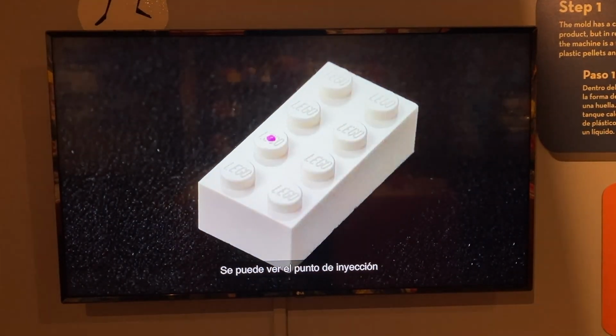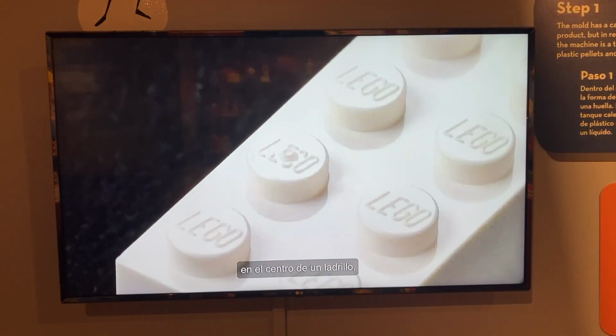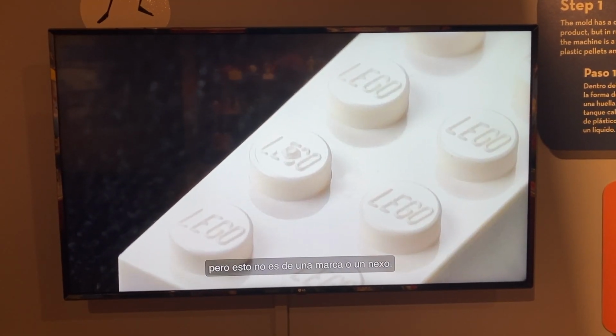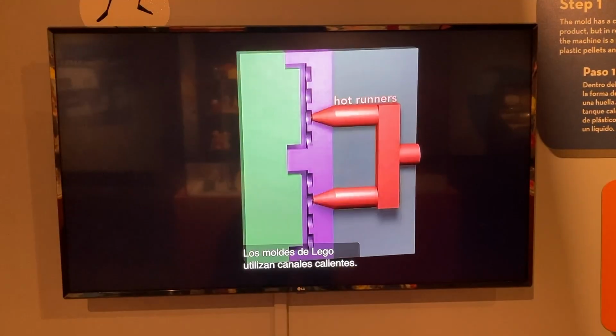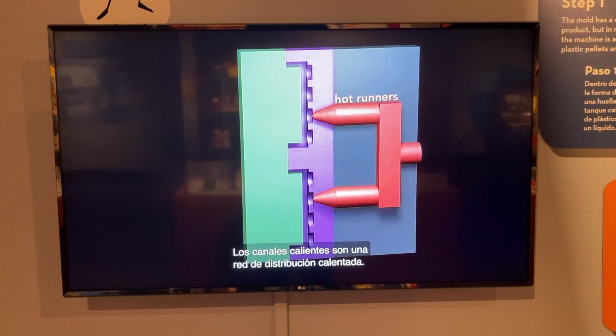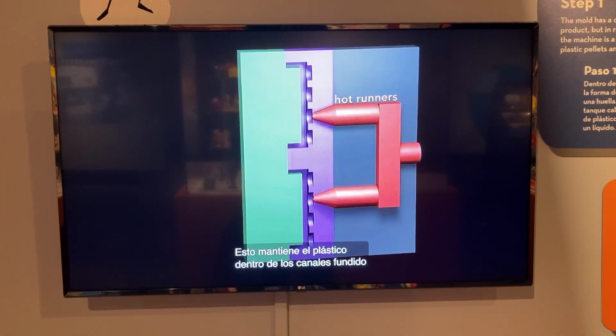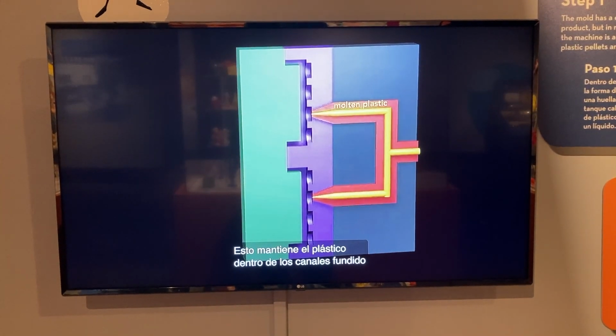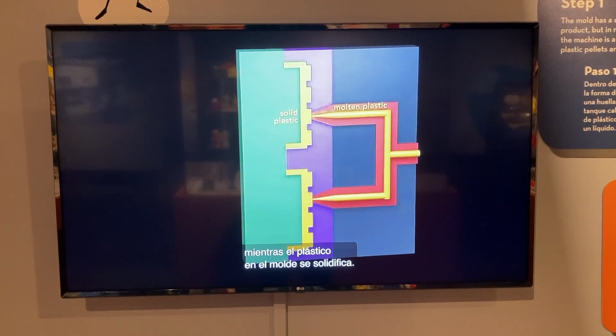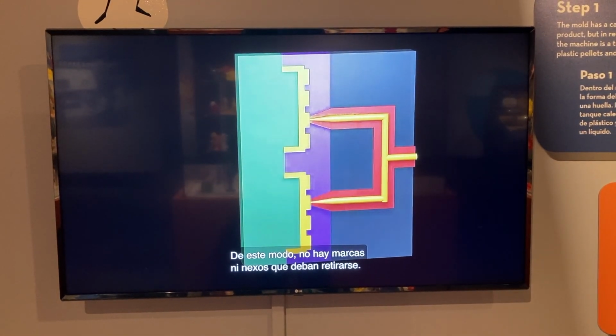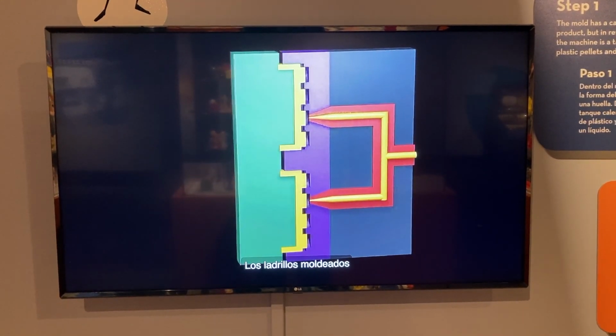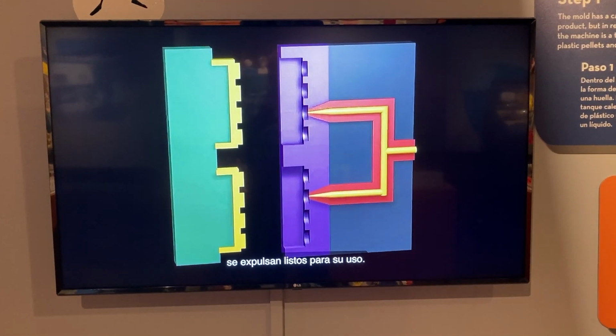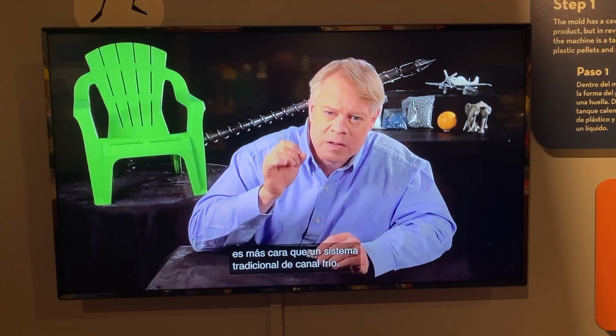One impressive example of injection molding is the Lego brick. You can see the injection point in the middle of a stud, but this is not from a gate or a sprue. The Lego molds use hot runners. Hot runners are a heated distribution network. This keeps plastic inside the runners molten, while the plastic in the mold solidifies. This leaves no gates or sprues to be removed. The molded bricks are ejected and ready to use. The downside is that this setup is more expensive than a traditional cold runner system.